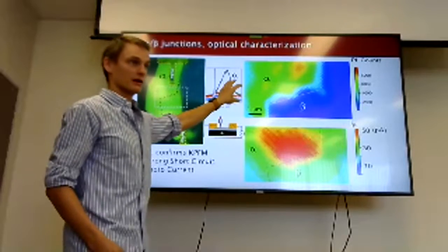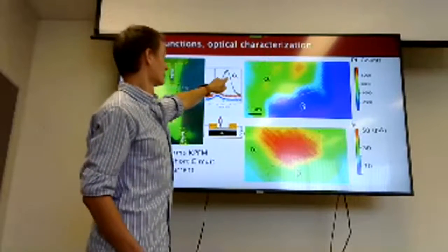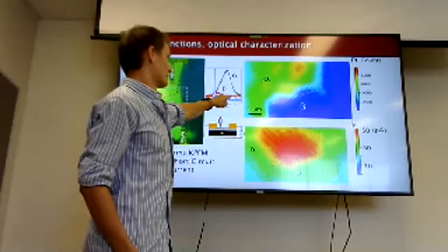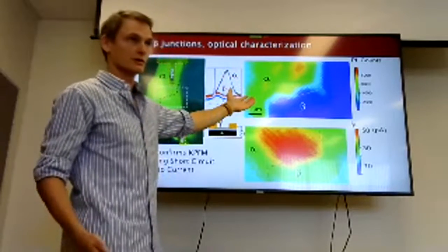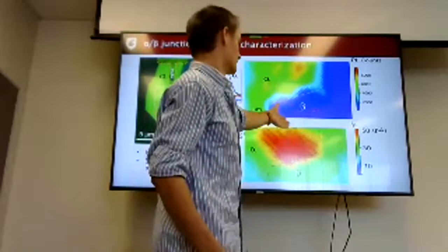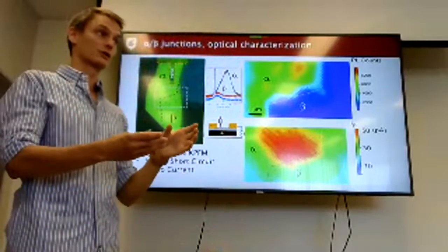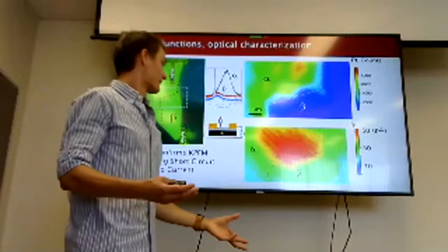for reference. And what we see here is the counts, where we do an integral over the fat part of this alpha peak, so that we can see the difference between alpha and beta. Right, beta is almost zero, alpha is non-zero. So we should be able to see alpha integrates to something greater than zero, beta integrates to zero. And sure enough, this agrees with the KPFM mapping. And if you have two measurements that say the same thing that work on different processes, you can be pretty sure that what you have is real.